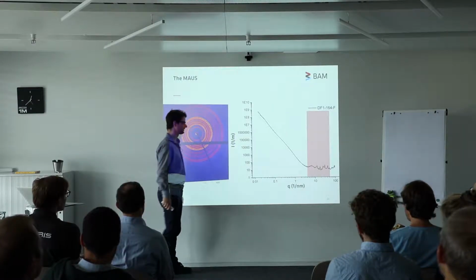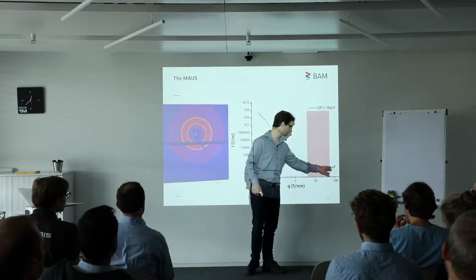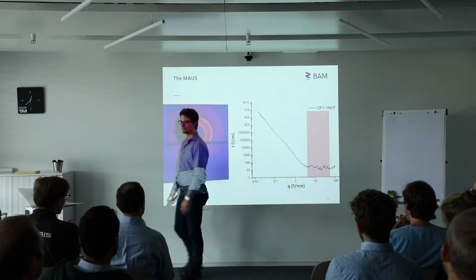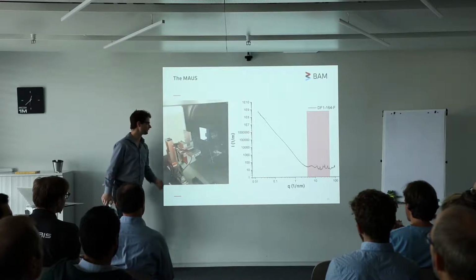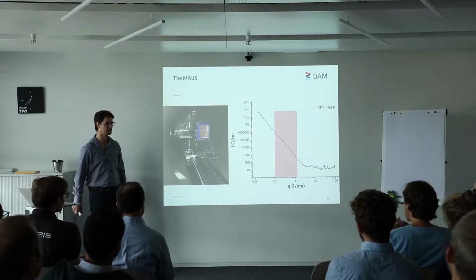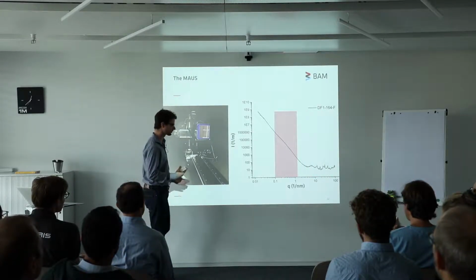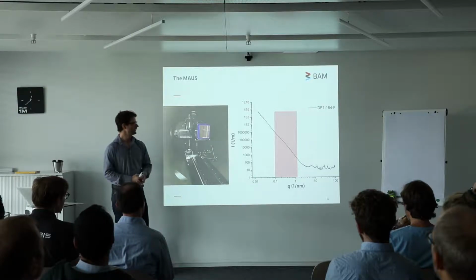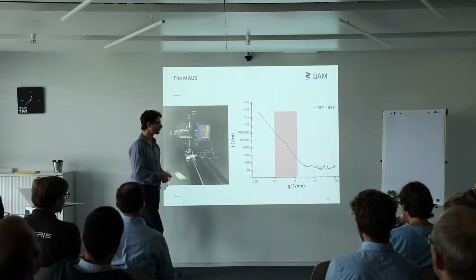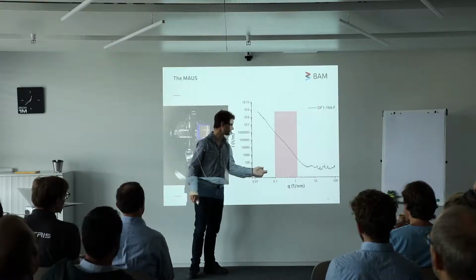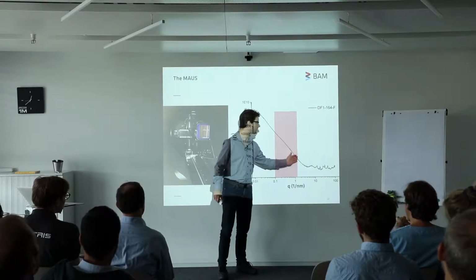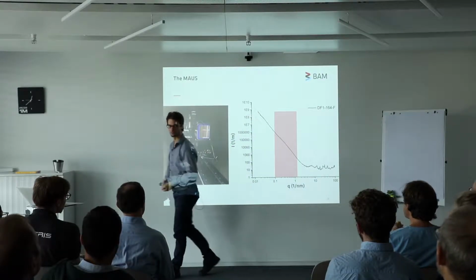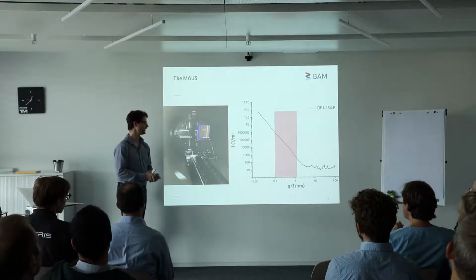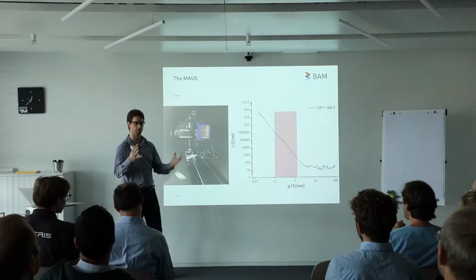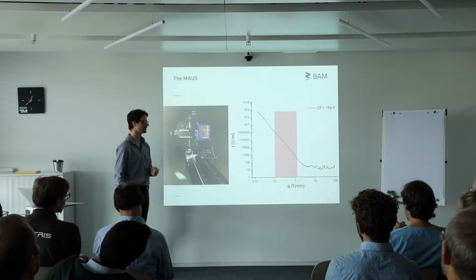That means we can detect crystalline materials in the wide angle regime. And when we move the detector further back, we can then detect the smaller scattered angles. And this then gives us a more comprehensive insight on the materials that we measure. In this case, the sample was from one of our colleagues from Birmingham University. This is a porous carbon support with iron carbide nanoparticles in it.